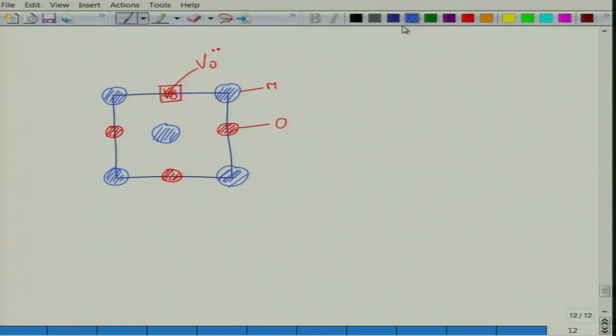And similarly this metal here will become VM. So you have a pair of vacancies without changing the stoichiometry. So M to O is fixed, okay. So this is called a Schottky reaction, and this reaction generally happens at the outer or inner surfaces or at dislocations, wherever energetics permits it.